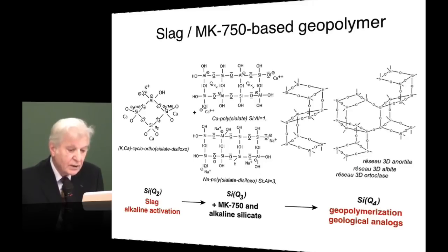If we look at what is happening on the structures themselves, so we start here. This is slag alkaline activation. We add metakaolin. We have a solid solution of two systems, calcium polysialate, Si:Al=1, and sodium polysialate disiloxo, Si:Al=3, and they interpolycondense into a three-dimensional network. The problem: